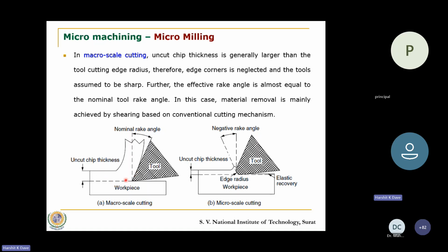So when you see this being carried out, the shape, the geometry of the cutting tool itself acts as a negative rake angle. The nominal rake angle is the real rake angle on the tool. So the nominal rake angle acts as the real rake angle, and that results in smooth machining and chips are formed. Continuous chips may be formed, depending on the type of workpiece, and that is how the cutting would take place with half or 1 mm of depth of cut.